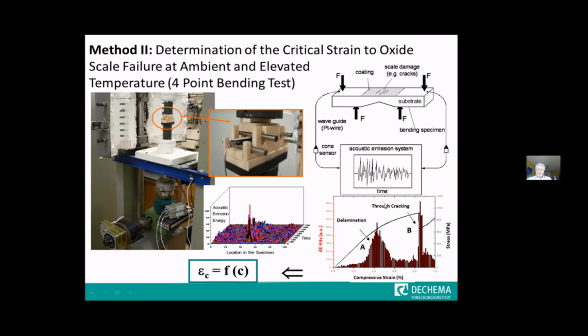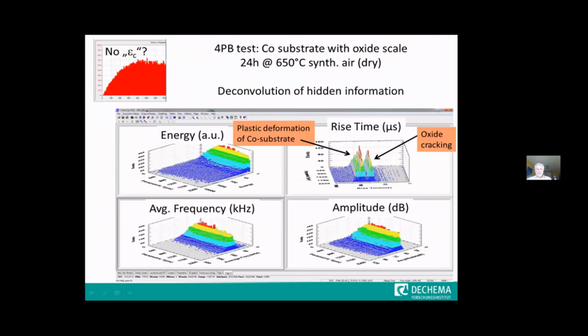So usually in this case, this example shows two failure steps. One is the delamination of the oxide. The other one is the through cracking under compressive stress. You see two such maxima, which means one effect is starting at a relatively low strain here, and the other one comes later. So what we want to do by these experiments is quantify the critical strain that leads to cracking.